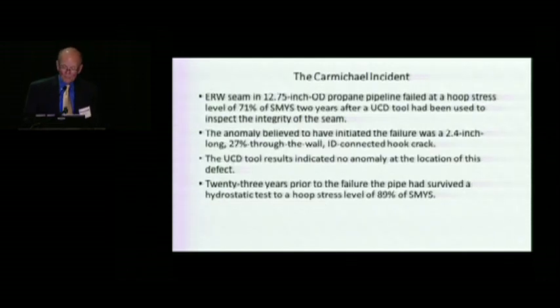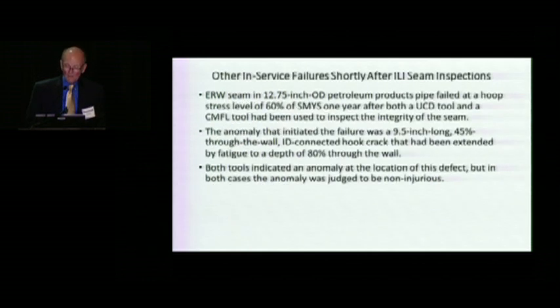The Carmichael incident itself, you could argue, was a pretty small anomaly, and it was. It was a 27% through the wall, 2.4 inch long hook crack, at least that's the consensus on the origin of the failure. There were probably some disagreements. But that pipeline failure was really the source of this study. There were other failures that we knew about, and probably more that I don't know about. One of them was a 12-inch petroleum products line in which both an ultrasonic crack tool and a circumferential magnetic flux leakage tool had been run, and yet within a year, a 9.5-inch long crack failed, and that crack, because it had been extended by fatigue, was 80% through the wall.